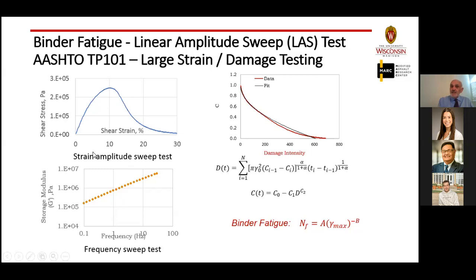Most of you that have worked with the IFIT test, you can see the resemblance of these results to what we get out of the IFIT. Now, this is a total coincidence, and we certainly don't use the data and analyze it in a similar way to what you do in the IFIT test. But it is very interesting to see the stage at which the binder is still behaving like a linear material until it gets to a peak where the damage, or the cracking, if I may call it, and we actually could prove there's cracking in the DSR, starts propagating, and then you'll see the slope going down just like what you do in the IFIT and so on.